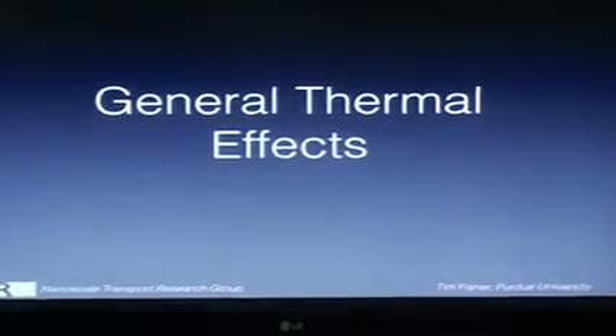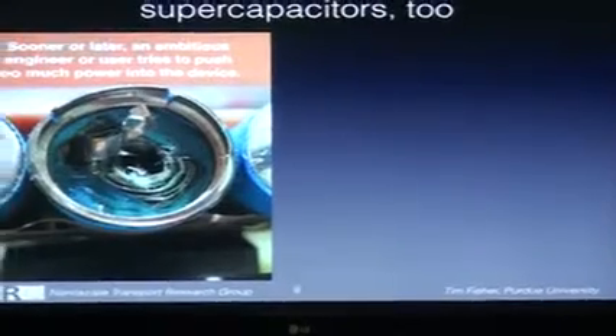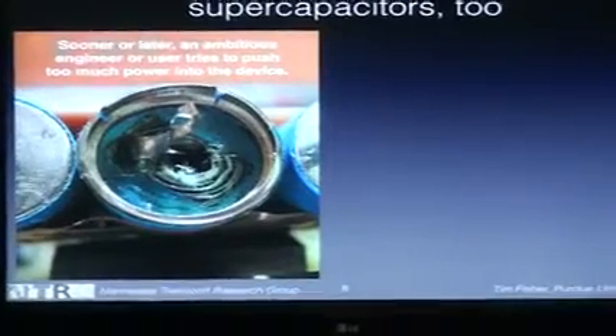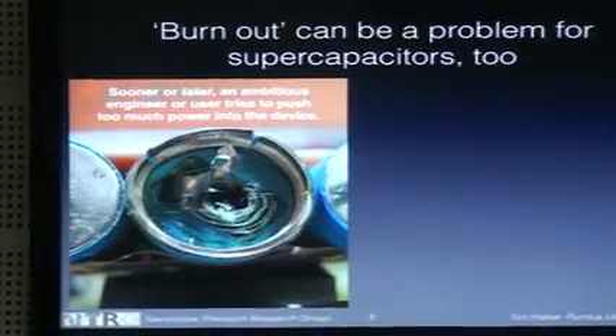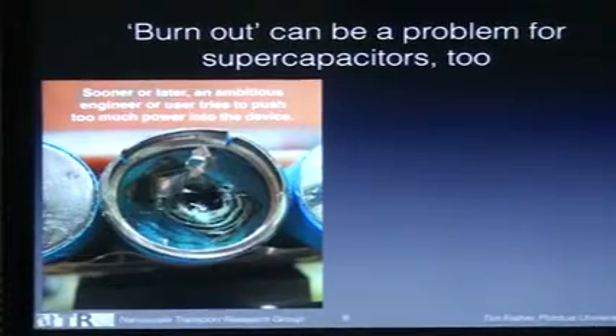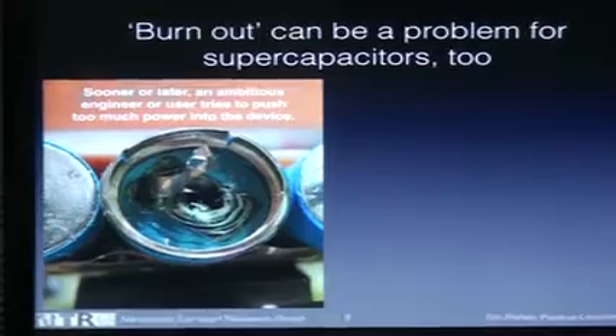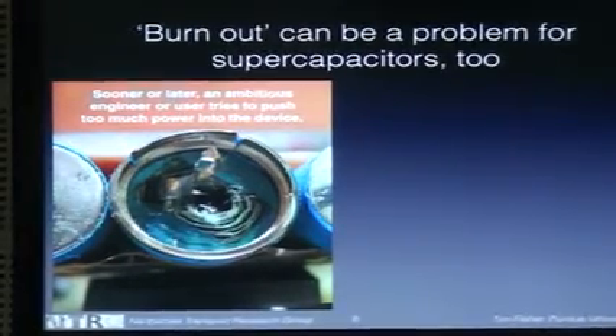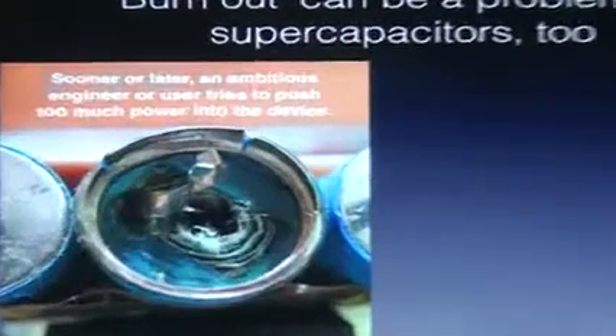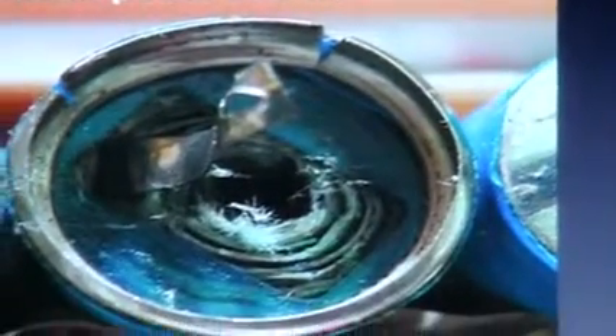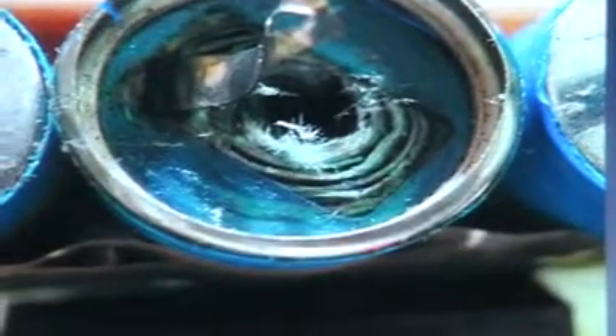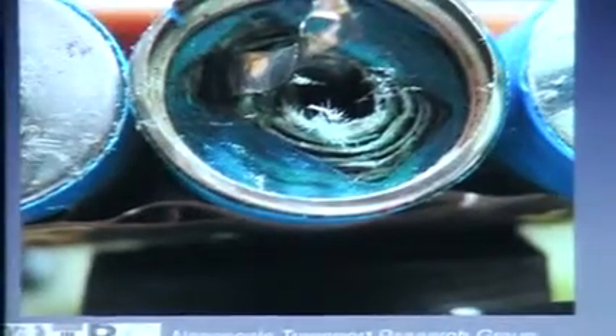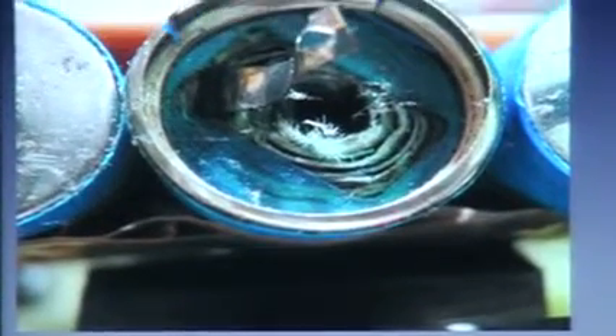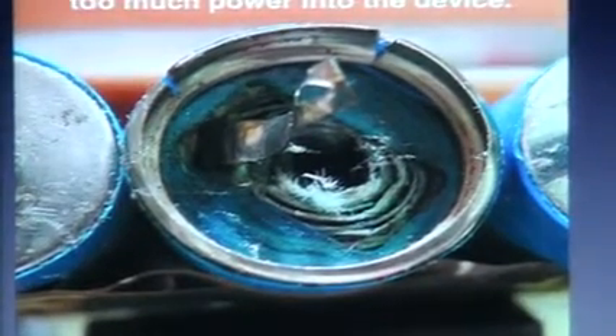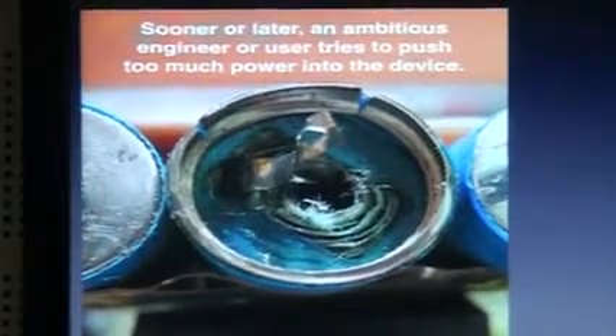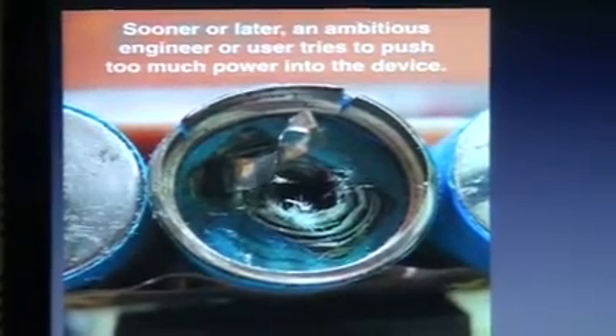So I'm going to move on to general thermal effects. And I would mention that even with supercapacitors, we've continued to say that supercapacitors tend to have better thermal behavior than batteries do. But even supercapacitors can burn out. Here's an example of something that was overcharged. Too much power was put into the device, and it couldn't handle it. The reactions couldn't keep up with the power that was coming in. And so what happened was you ended up having a big resistive effect, which produces higher temperatures. Ultimately, you could cause burning of the material, which then causes the device, which is sealed, to unseal. So gases are released and so forth.